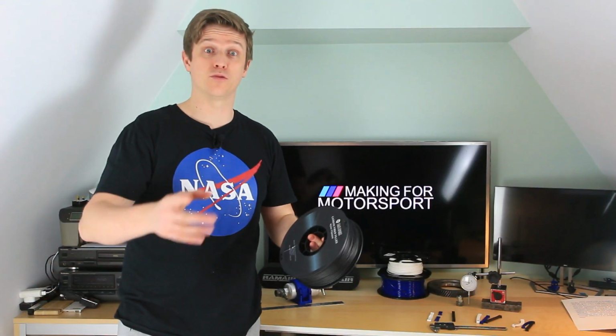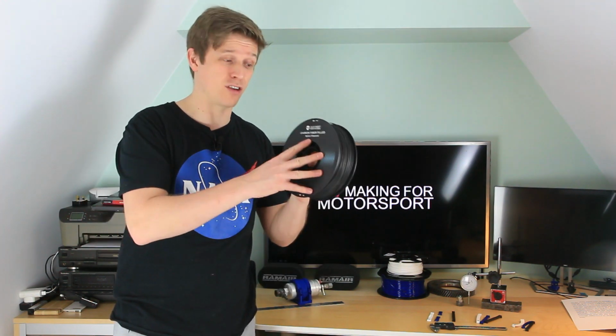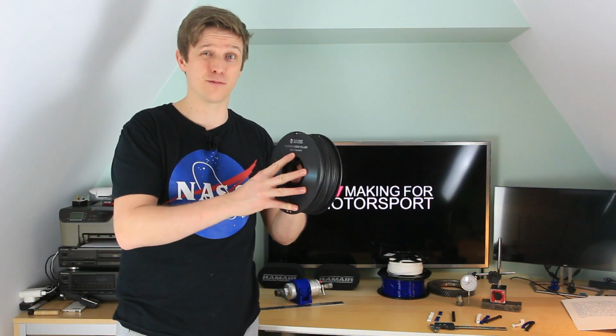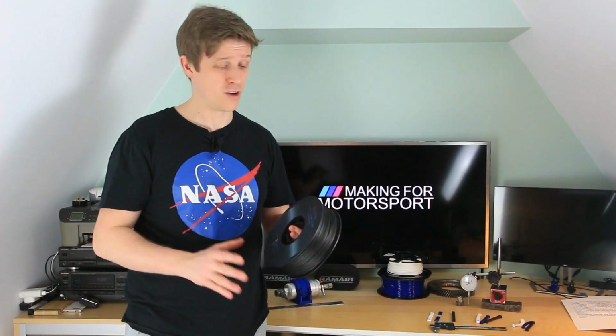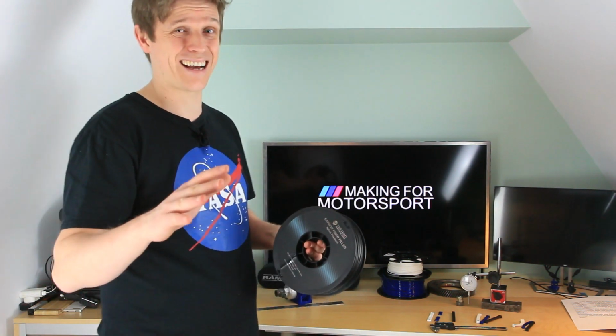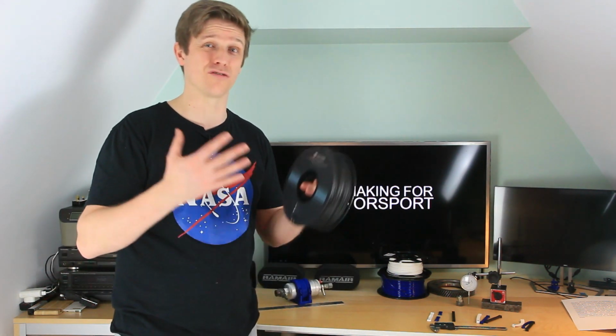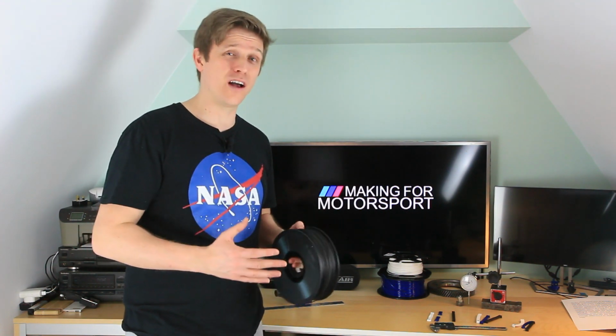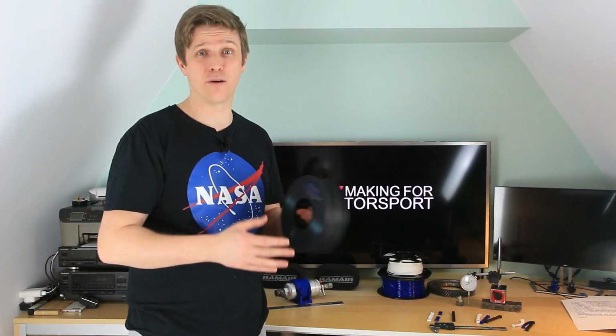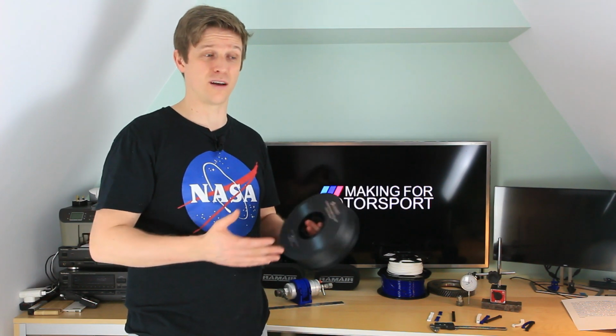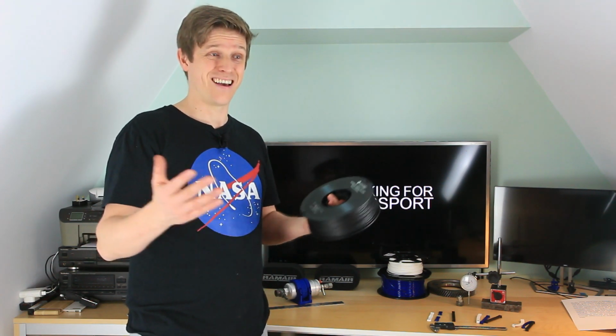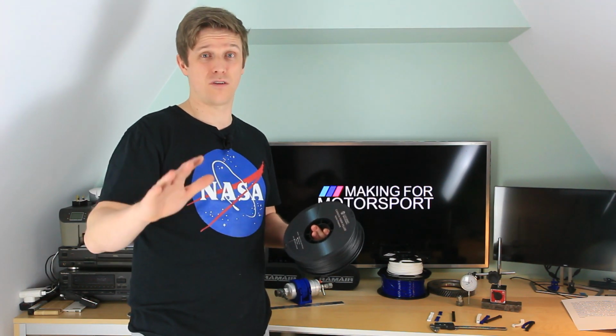So what have we learned? Well, number one, straight off the bat, this carbon fibre nylon from Sainsmart is very temperature resistant. The test we got, we didn't get any sag until 175 degrees, which is great. I'm sure if we used a higher load, we'd get more sagging at a lower temperature, but certainly the signs compared to all the other filaments, even annealed PLA, are great.